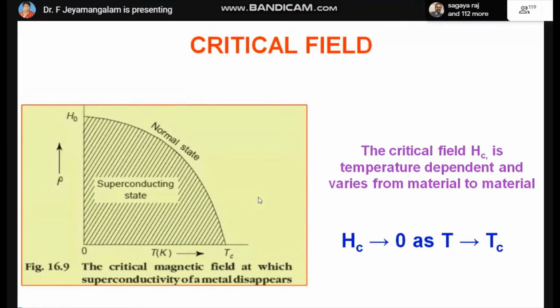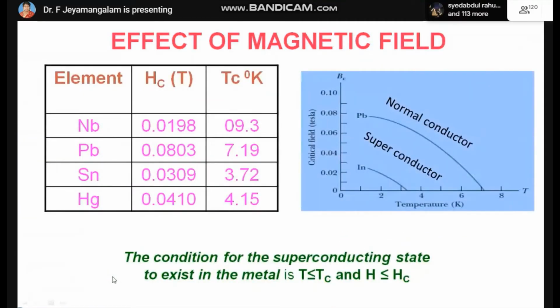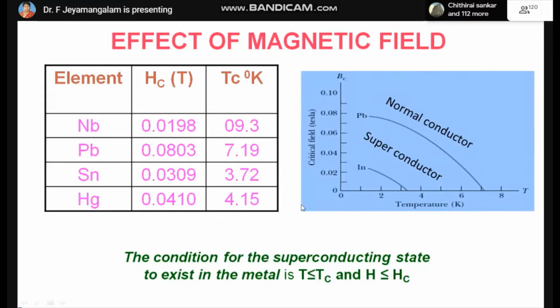As I have already told you, the temperature at which the material loses its electrical resistivity at zero magnetic field is known as the critical temperature. I have given you the element along with the critical field and critical temperature. For example, when I take lead, the critical field is 0.0803 Tesla and the critical temperature is 7.19. You can see that in the graph also, it is 7.19 along the temperature and the critical field is 0.08 along the y-axis. So below that particular curve, the lead will exist as a superconductor, and if we increase the temperature or increase the field, then it will become a normal conductor. So I have given you the condition for the superconducting state.